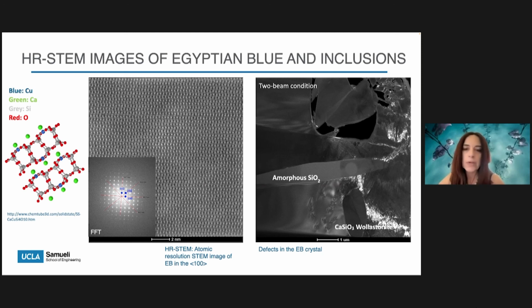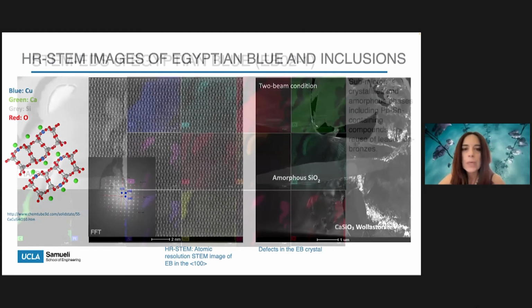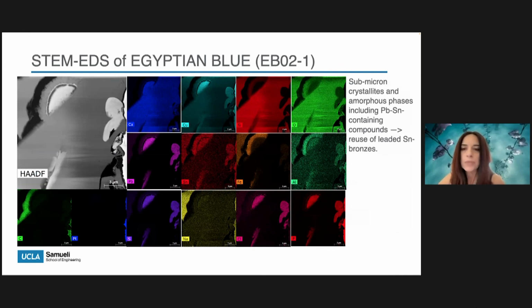By indexing the diffraction pattern with fast Fourier transform, we were able to measure the lattice parameters, which were very close to the reference values we get for natural mineral cuprorivaite. To the right, the two-beam condition shows the presence of defects in the single crystal and the presence of calcium silicate and amorphous silica. Further analysis with STEM EDS focused on other submicron amorphous and crystalline phases found in the defects of Egyptian blue. Here you can see maps of element abundances corresponding to the high angle annular dark field image that you see on the left.